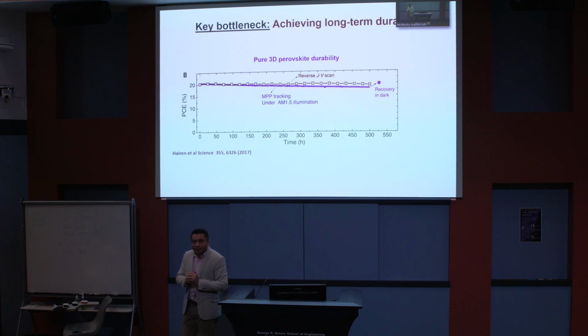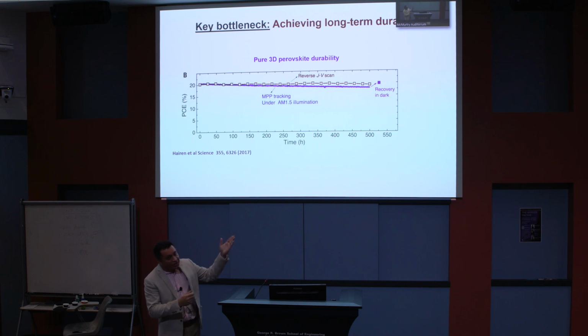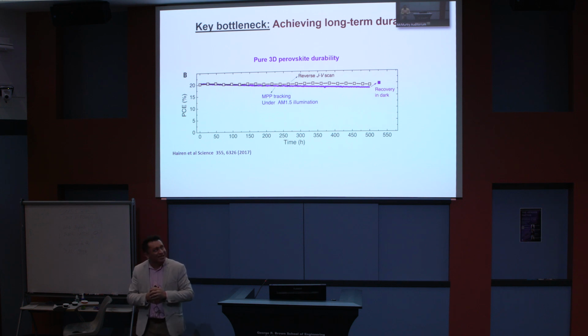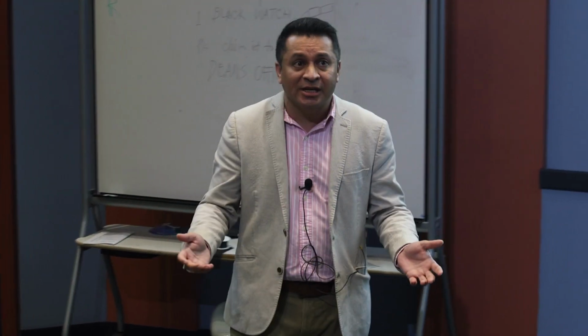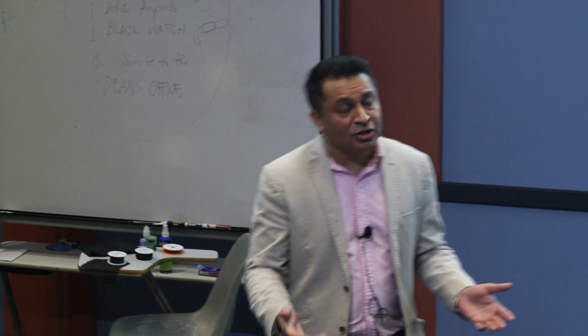However, there is a problem. If you look at a curve that is produced from a photovoltaic device, from a perovskite solar cell, you'll see that it starts off at a nice number, about 20%. But then after 400 or 500 hours, you'll see that it has lost some efficiency. And that is not good enough, because what we are trying to make is a technology for photovoltaic devices or solar cells that can last for 20 years on a roof. And so that was not good enough.